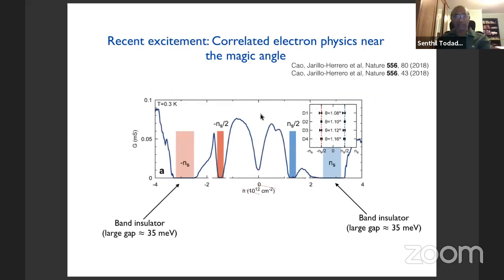So the recent excitement started 2.5 years back with experiments done by my colleague Pablo Jarillo-Herrero at MIT. Quite dramatically, his group discovered that if you take nearly magic angle twisted bilayer graphene, all kinds of correlated electron physics is apparent. This is a plot of the conductivity of one of the devices they made, plotted as a function of the carrier density, where n equals 0 is charge neutrality. The scale for the carrier density is 10 to the 12 per centimeter squared, so it's an extremely low density system.